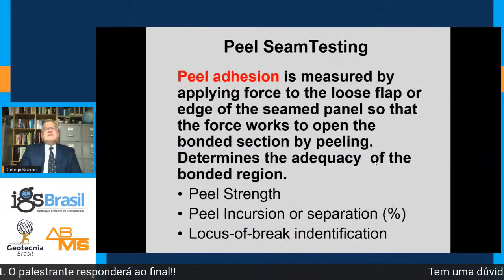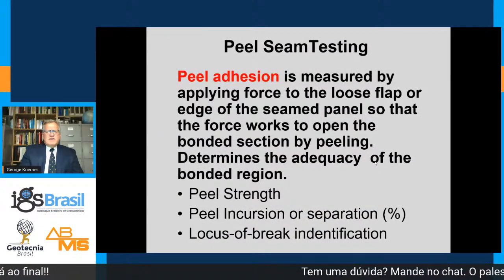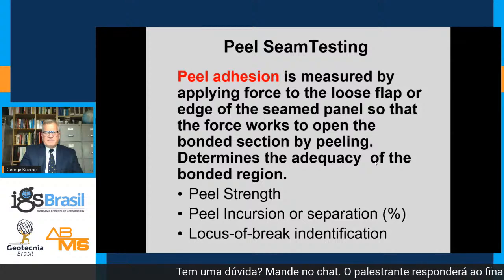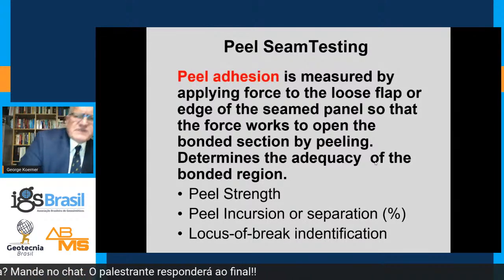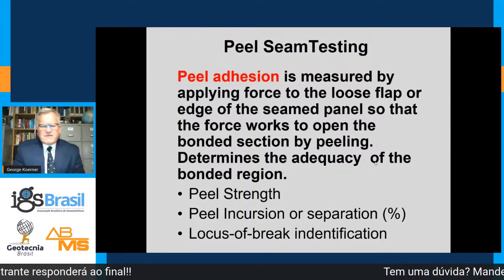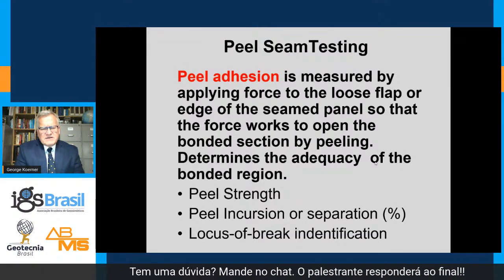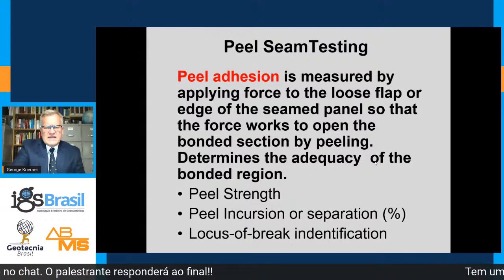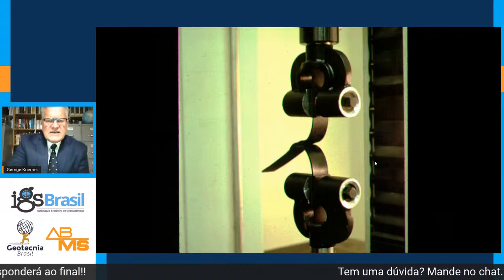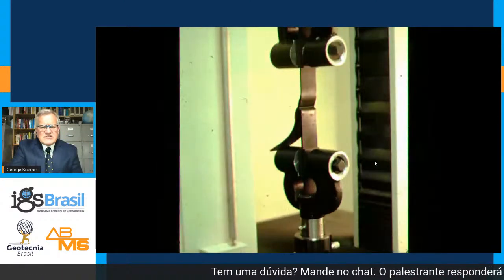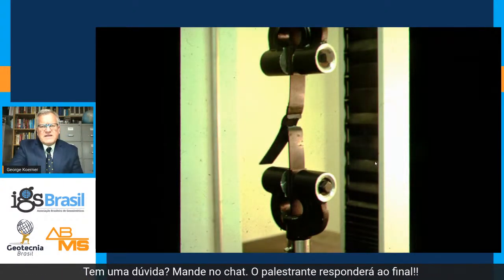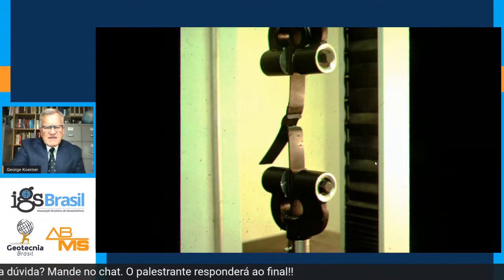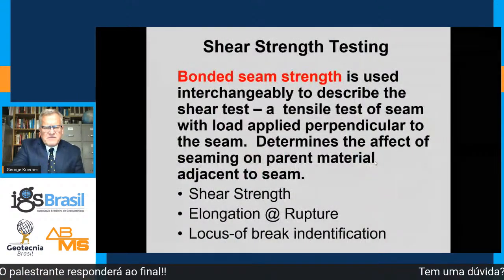As far as the peel testing is concerned, we're looking at peel adhesion of the material. This is a measure of pulling the materials apart with 2 flaps. You're looking for 3 properties: a peel strength, a peel incursion or separation, and then a locus of break. In this case, you see it's set up in a continuous rate of extension. We're now pulling this typically at 50 millimeters per minute, and then have a ductile failure of the material.